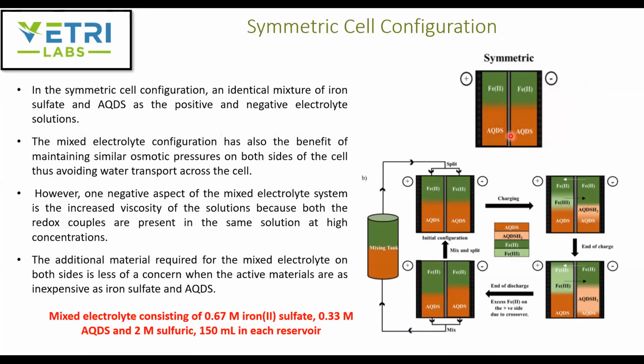So the first approach that they've used to solve the crossover is using a symmetric cell configuration. In the symmetric cell configuration, you have an identical mixture of both iron sulfate and AQDS on both the positive and the negative side. So the solution is 0.67 molar iron sulfate with 0.33 molar AQDS and 2 molar sulfuric acid, with a total volume of 150 ml in each reservoir. The advantage of this mixed electrolyte configuration is that they have a similar osmotic pressure on both sides of the cell, so it avoids water transport across the cell.